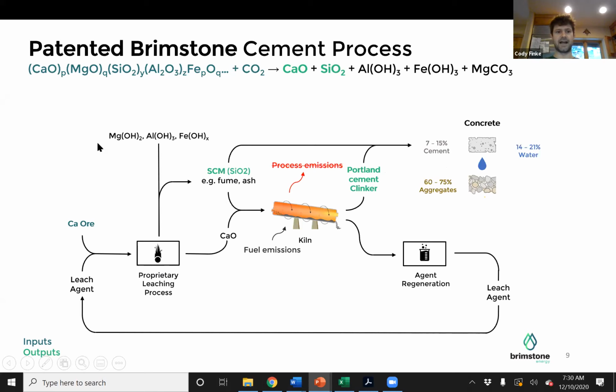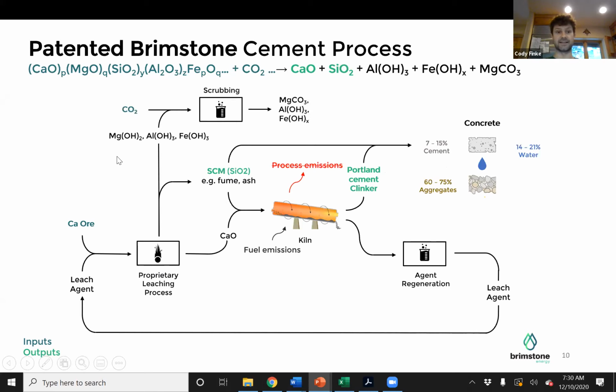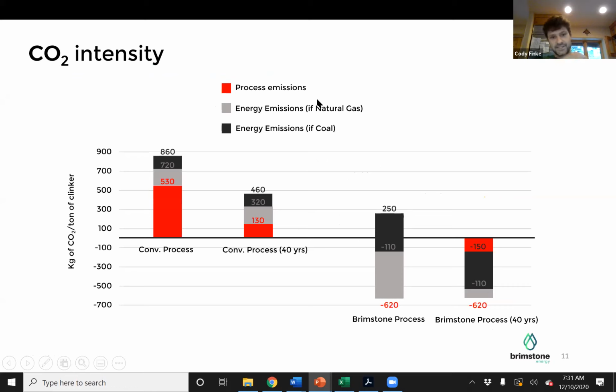And then finally, if there's high magnesium contents, which typically there are in any rocks that contain calcium, the waste product magnesium dihydroxide, or brucite, will naturally carbonate, which means there's nothing we can do about this carbonation. However, if we scrub our flue gas, which is typically already regulated because all flue gas contains SO2, so you have to scrub it, and if we put our flue gas through the scrubber, just like we normally would, we'll make an enormous amount of magnesium carbonate. In fact, it turns out that per ton of cement, a typical rock will actually have 620 kilograms of CO2 of negative emissions capacity.